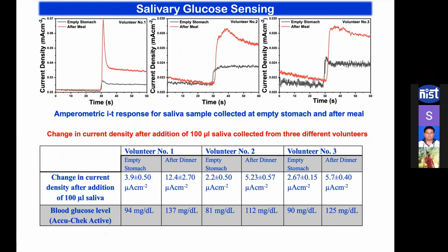And more importantly, we have conducted another experiment. This is an interesting result. Here you see we compared our sensor response with commercially available glucometers, and we collected saliva samples from 3 volunteers before and after dinner. The black one is empty stomach and the red one is after meals. Interestingly, after meals, the glucose concentration in saliva increases. Already we know that, and here is the sensor response, the change in current density after addition of 100 microliter saliva. This is for empty stomach, and this is after dinner.